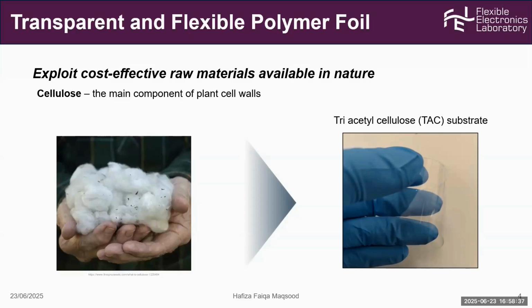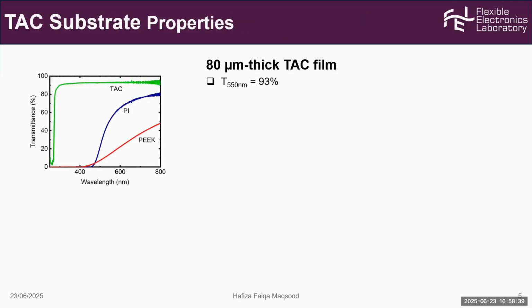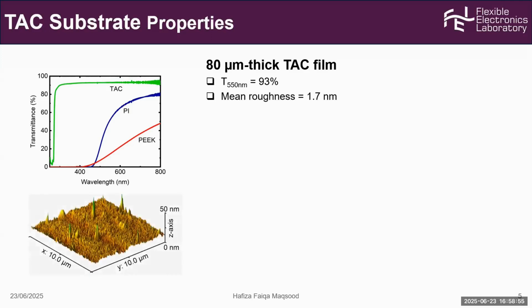We use the TAC substrate, and before any fabrication, the properties of the TAC substrate were evaluated. First, we measured the transparency in comparison with polyimide and PEEK. TAC showed 93% transparency. In addition, we did the AFM measurements. Its value is 1.7 nanometer, a low surface roughness that is very ideal for electronic applications.